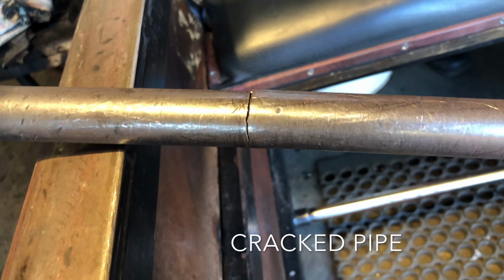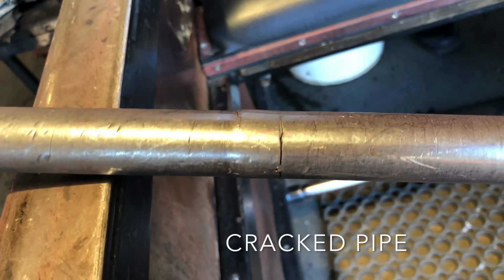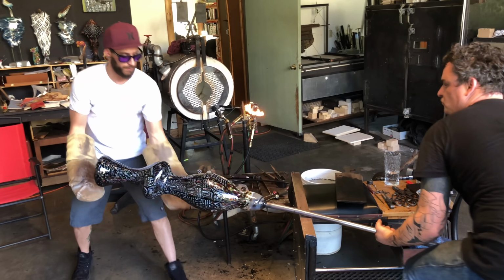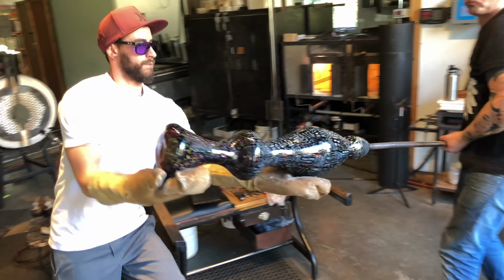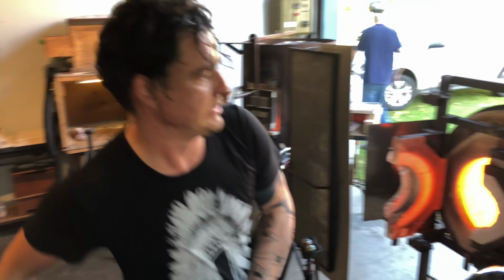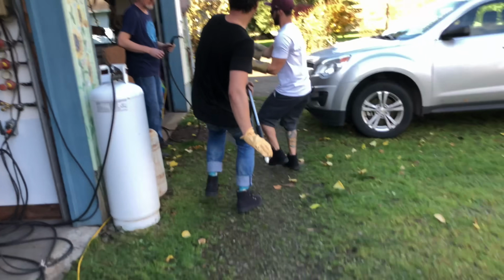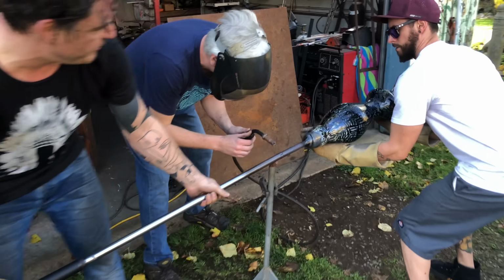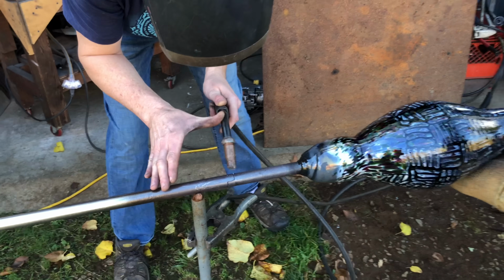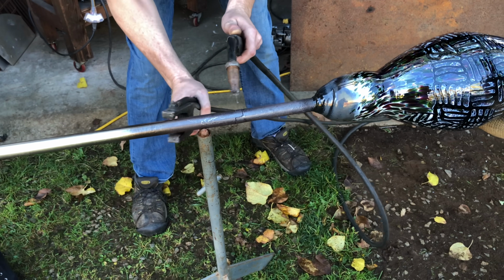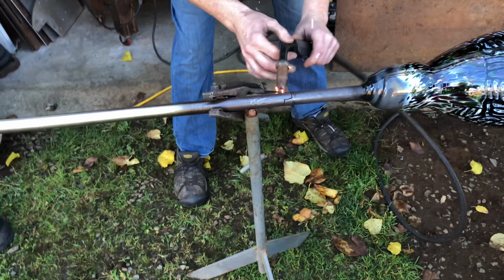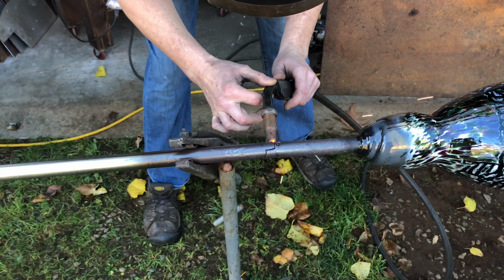Unfortunately, at this stage, Jasen noticed a crack in the pipe. This was an emergency situation that had to be dealt with immediately. Jasen moved one of his welding rigs outside, Chris put on the Kevlar gloves, and Martin ran the piece outdoors, where they set it up on a yoke and hurriedly tried to tack the 2 sides of the blowpipe together before the piece fell onto the ground.